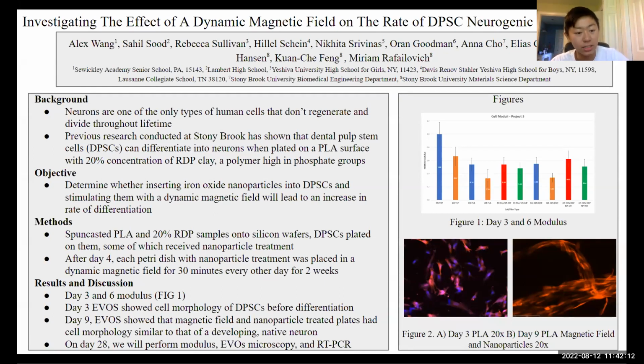And what we were expecting on these controls is for our day 6 modulus following neuronal media switch, we were expecting much lower moduli results because neurons are supposed to be much softer than the dental pulp stem cells. However, what we also saw on day 6 following neuronal media change was that the ones treated with nanoparticles and the dynamic magnetic field were much more rigid than the ones not treated with the magnetic field. And we believe that this is the case because the nanoparticles have attached onto the cell membranes, and therefore, since they're made out of iron oxide and gold shells, they're much rougher and much more solid than the typical cell membrane.